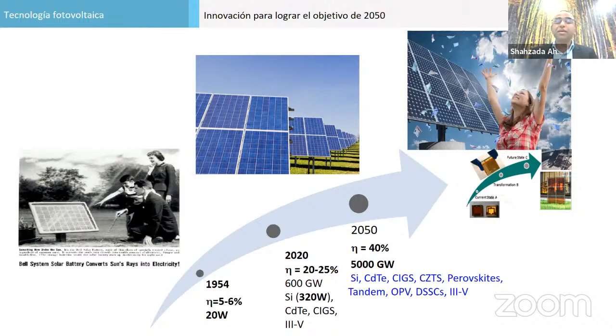We also have cadmium telluride, CIGS, but these are technologies waiting at the market entry, and it is very difficult to say whether they will achieve full market penetration or not. And by 2050, if all this technology can bring down the cost, we also need a contribution from silicon, cadmium telluride, CIGS, perovskite, tandem perovskite, OPV. So if all these technologies or some of them can compete, then we can achieve the 5000 gigawatt of installation, and we can push the performance to 40% efficiency.